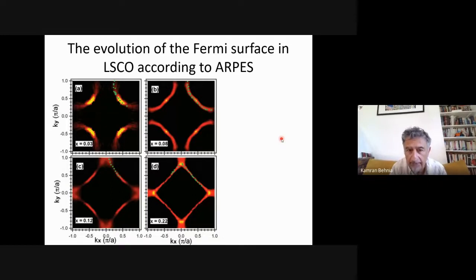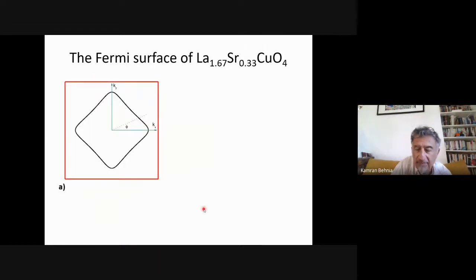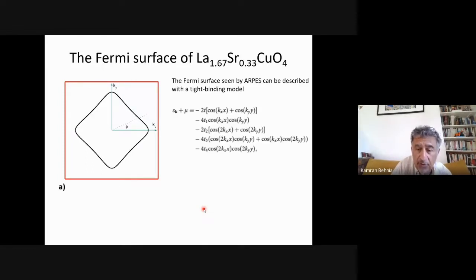Now let's come back to cuprates. There is one important ingredient about the cuprates, which is that the Fermi surface is well known. And so this is the evolution according to ARPES. I am interested in what happens for the extremely overdoped cuprate. Here you can see that this hole-like Fermi surface becomes electron-like. And actually, at 32%, the Fermi surface is very well given by a tight binding model. This is what you expect also according to LDA calculations, if there was no Mott transition. All of the numbers fit what the ARPES Fermi surface at this doping is given.